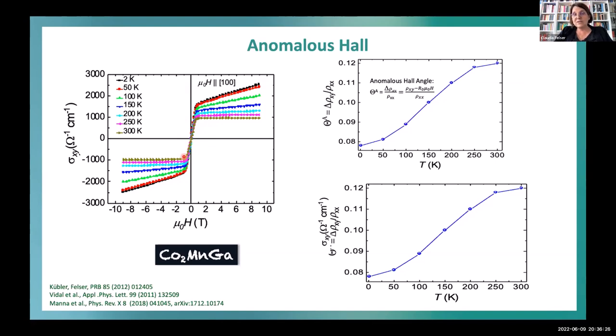But this now we know, and you know also, it's not true, because especially if you have topology in place, this jump scales really with the topological intrinsic properties. And this is even something which I think is the best measure to prove that some magnetic compound is topological. So we then can even determine the Hall angle. It's very similar to the spintronics people's spin Hall angle, because this is based on the same principle.